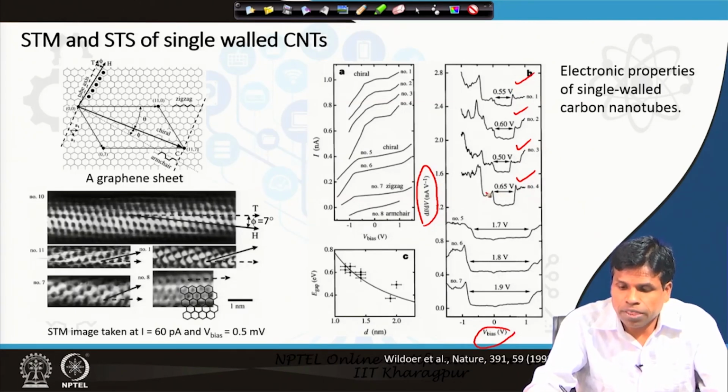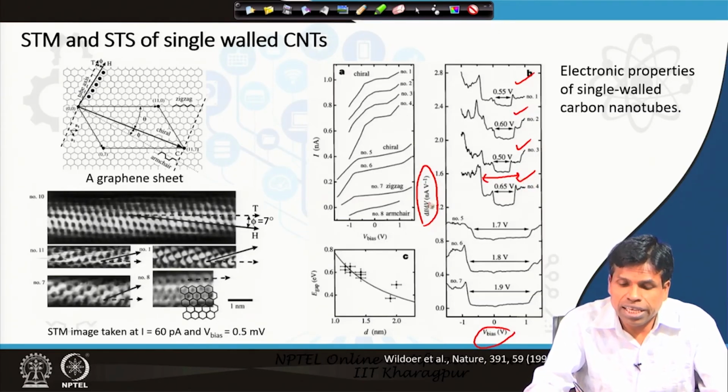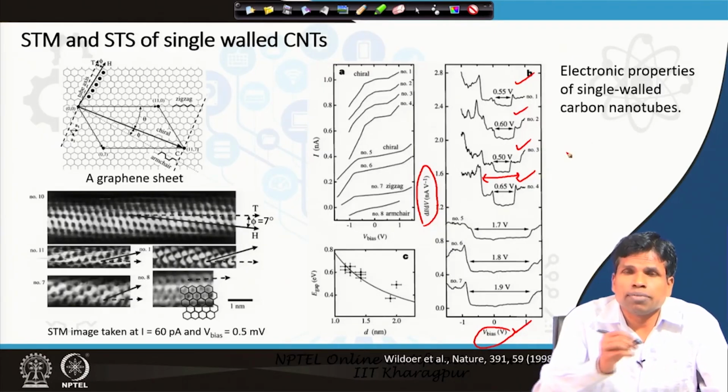This is the energy gap. These are the density of states. In addition to that, there are also secondary gaps because of other effects, which are beyond the scope of this lecture. But this dI/dV versus voltage can be utilized to measure the band gap or electronic properties of a single wall nanotube or single features which are very small in size.